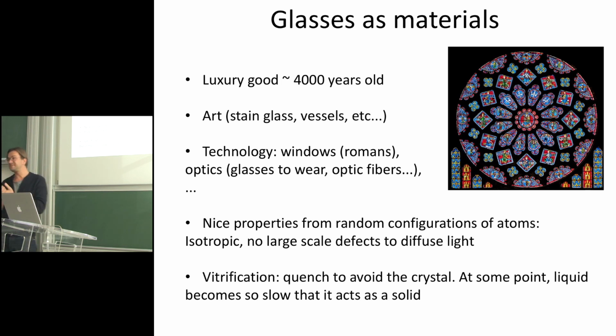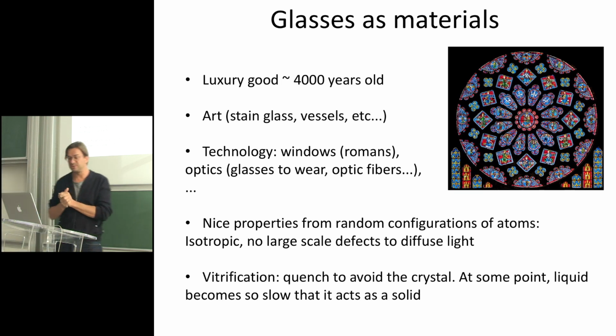And many of the nice properties of glasses come from the fact that at a microscopic level, they are actually disordered structures. They are isotropic, and they don't have big defects like grain boundaries because they don't have this long-range order. And thanks to that, they cannot diffract light and things like this, and so they can be nicely transparent. So in this talk, we're interested in the making of a glass, which you make from a liquid by quenching it. The idea is you have to choose a good chemistry so that the crystal is not too favored, and then you rapidly quench the liquid, and at some point, the liquid becomes so slow that it starts to act as a solid.